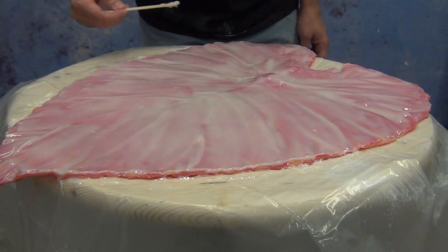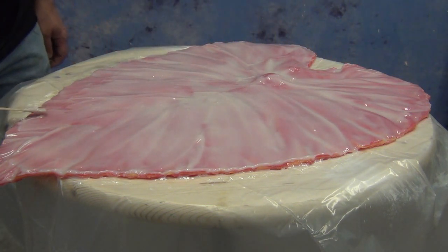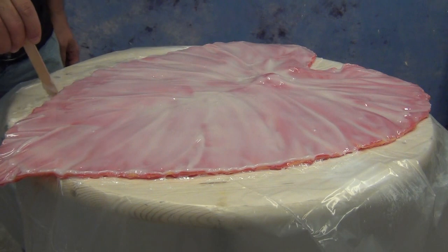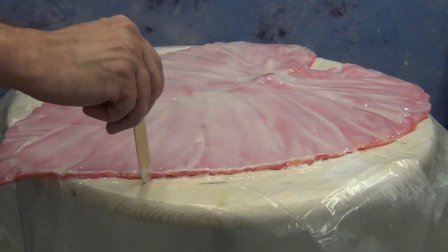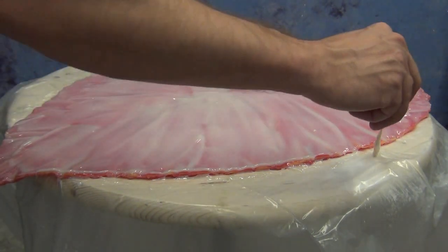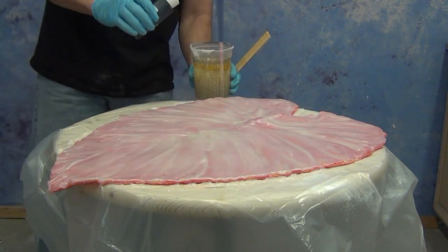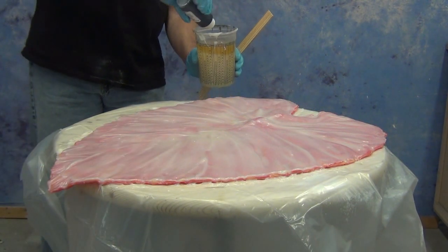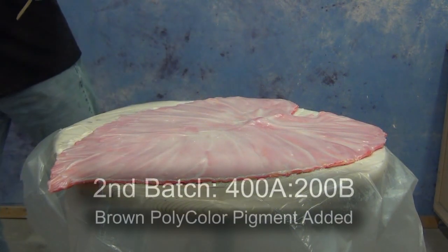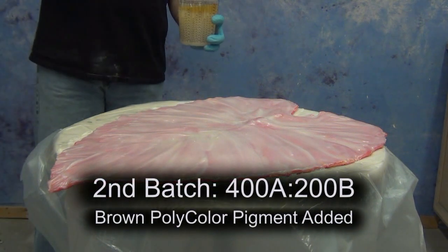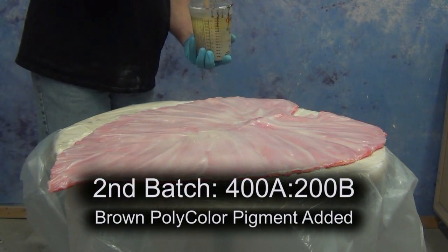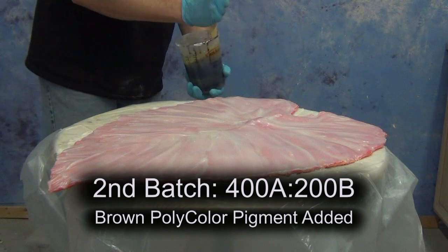So we're applying this in two layers. This first layer we applied is just under 1/8 inch thick. And obviously it's going to be a little thicker and a little bit thinner in some areas, but we want that to be as uniform as we can get it. And once that cures to a point where we can apply more resin without disturbing that first layer, we're ready to mix up our second batch.